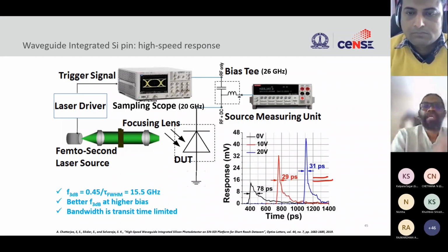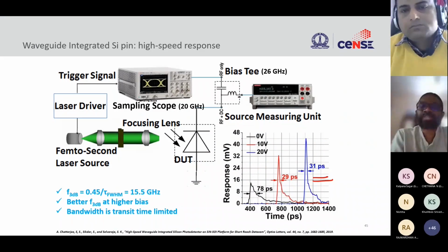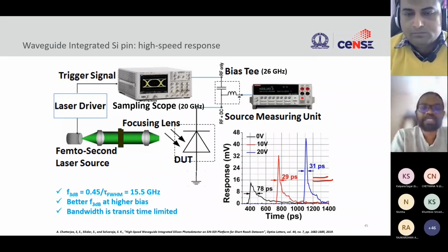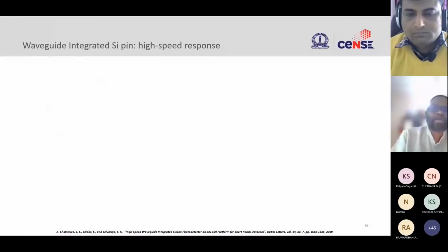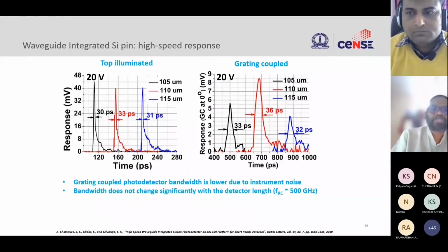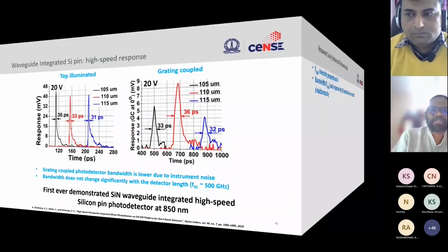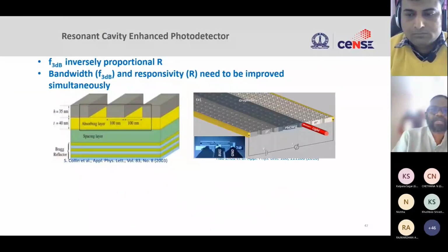And if you combine this, right, 0.4 amp per watt with 15 gigahertz, so we were able to demonstrate that using a circuit platform, one can actually achieve better responsivity than what a thin film detector can do, and also get speeds on par with thin film detectors. Okay, so this is something that we did.